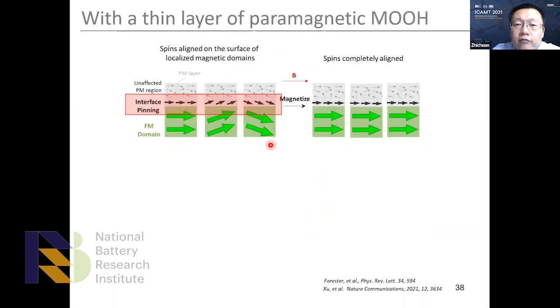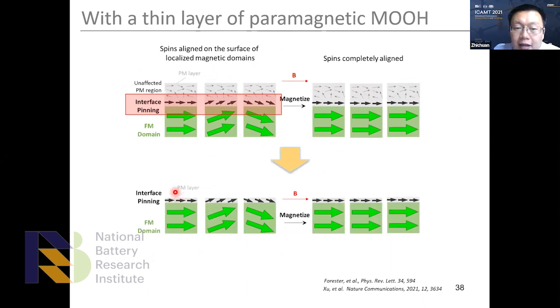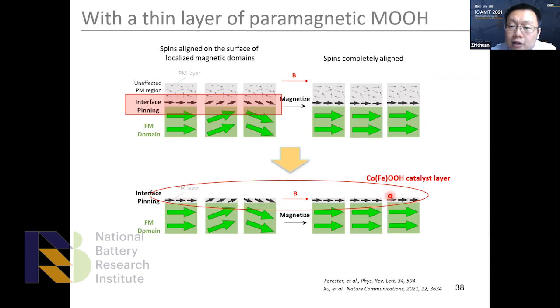So now let's see, if we make this layer very thin, just like the case I just showed with cobalt oxide here, if I make the top layer very thin, just a few nanometers, then we are able to control the overall paramagnetic layer, the spins in the paramagnetic layer. So in this case, for example, exactly the model material we are talking about here is the cobalt iron oxyhydroxide catalyst layer, which is the paramagnetic layer on the top, and we have ferromagnetic cobalt iron oxide as a substrate. So this actually explains why we observed very high activity for this cobalt iron oxyhydroxide.